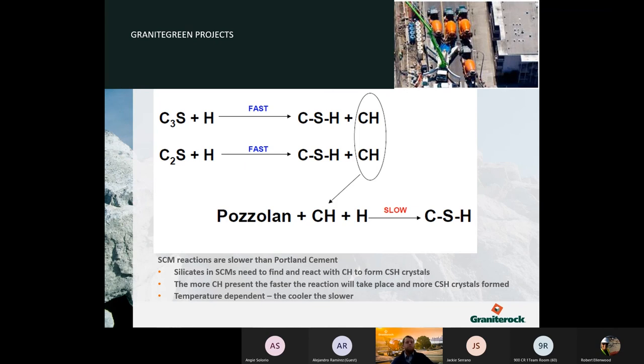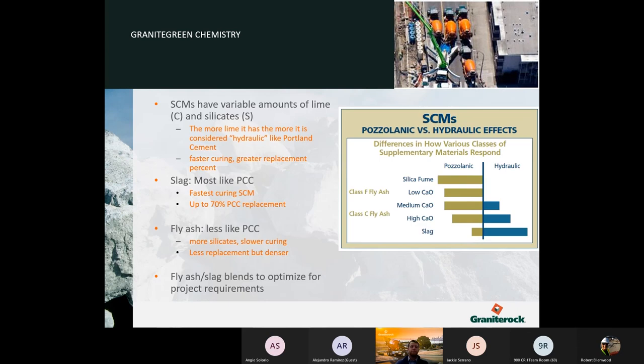SCMs react slower than Portland cement. The silicates in SCMs need to find and react with the free CH to form new CSH crystals. The more CH present, the faster the reaction can take place. And it also depends on temperature. So the cooler, the slower.